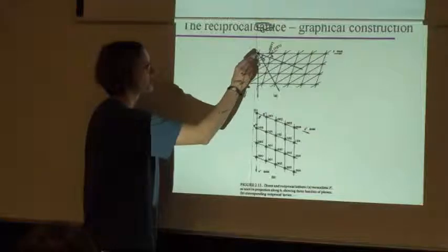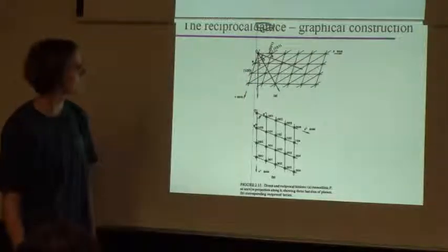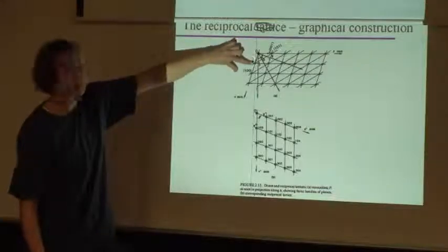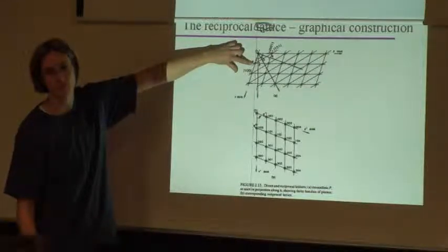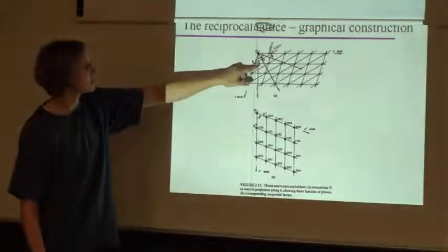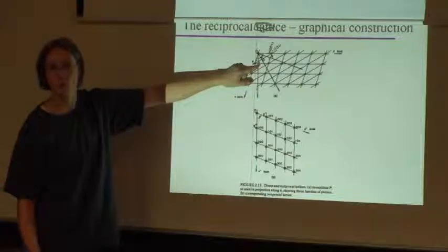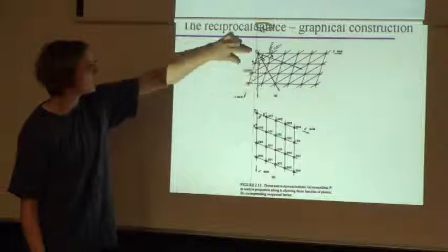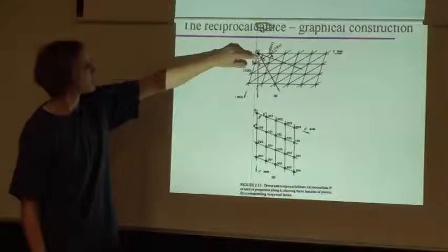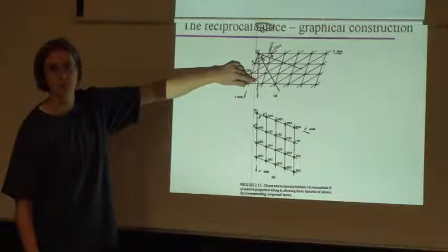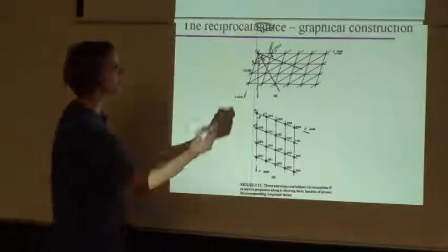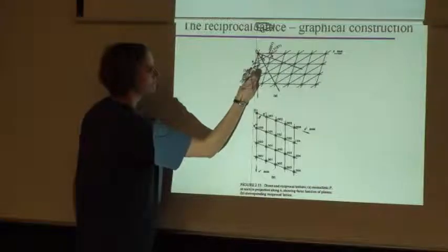But we pick our origin up here, and if this, for example, was 1, okay, very simple A-axis 1, then the distance we should mark on this one should also be 1, because 1 over 1 is 1, right? If this length was 2, what distance should we mark here? 1/2, right? So it doesn't really matter what that distance is. Let's say it is 1.